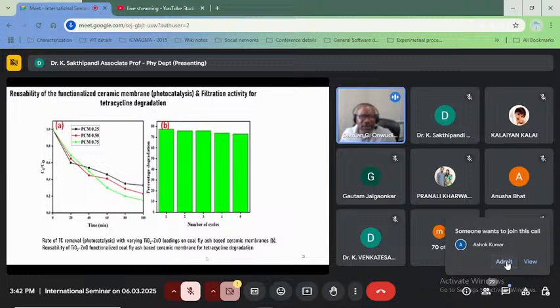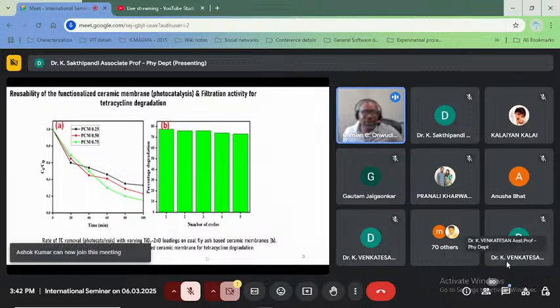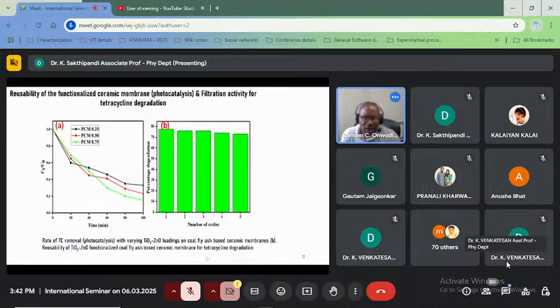And so we tried to check the reusability of this ceramic membrane after several runs, and found out that only a minimal amount of efficiency was lost even after 5 cycles. So having done with photocatalysis, we now wanted to look at filtration, because this is a hybrid material, combining photocatalysis and filtration processes. So we're done with photocatalysis, and we also tested for filtration.